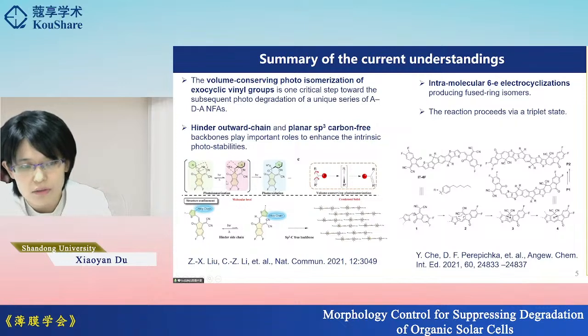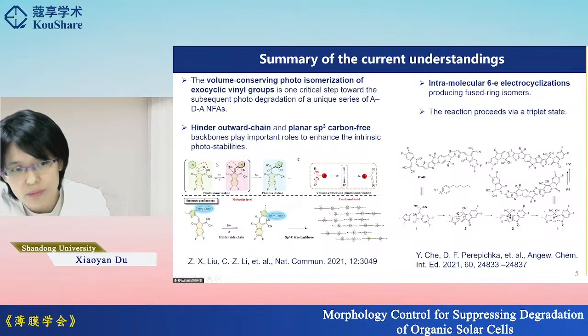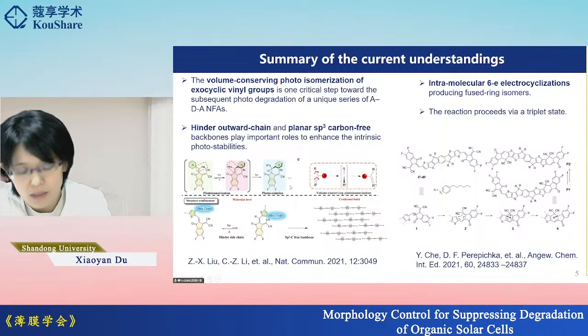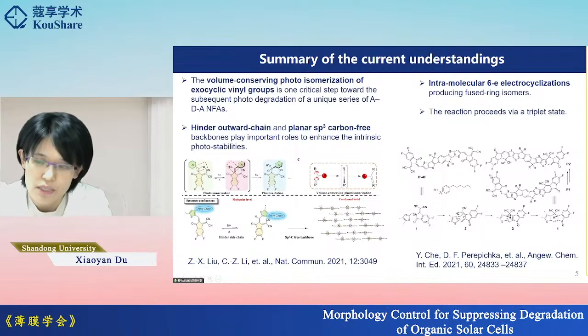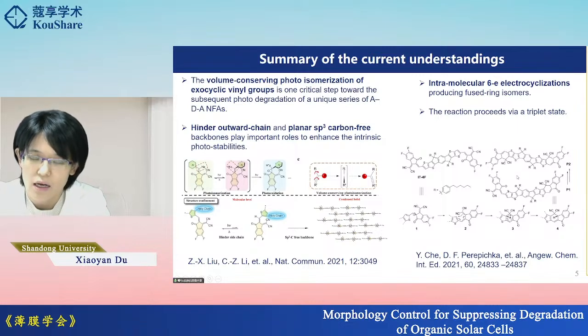In this work, the authors revealed the volume-conserving photoisomerization of this end group in this position. And this photoisomerization will lead to subsequent photooxidation of the materials. And this is the way the material degrades. And in this work, the authors showed that even without oxygen, this kind of material can undergo this intramolecular